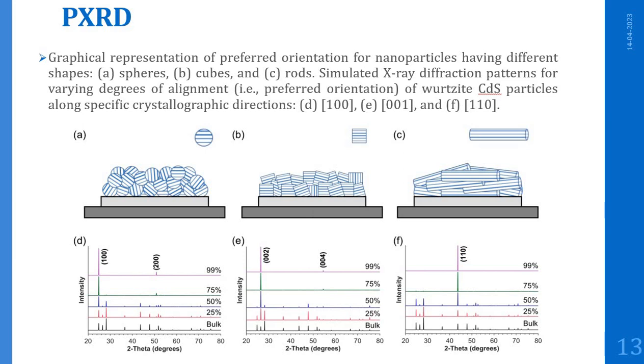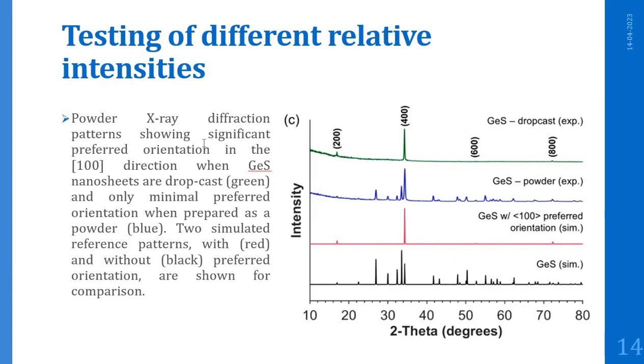Later on, there is the testing of the different relative intensities. To test if different relative intensities are due to preferred orientation effects, the same sample can sometimes be prepared for XRD analysis in ways that either minimize or maximize preferred orientation. For example, you can see the figure here. That is germanium sulfide, and the corresponding XRD pattern is shown in this graph. This is experimental data for the germanium sulfide nanosheets drop cast onto the XRD sample holder.